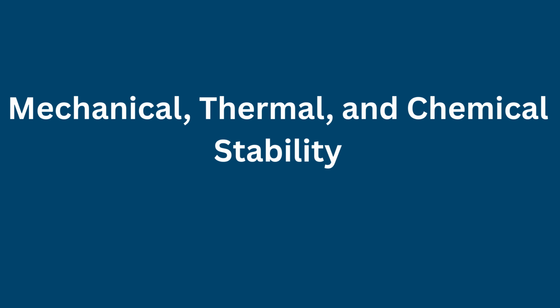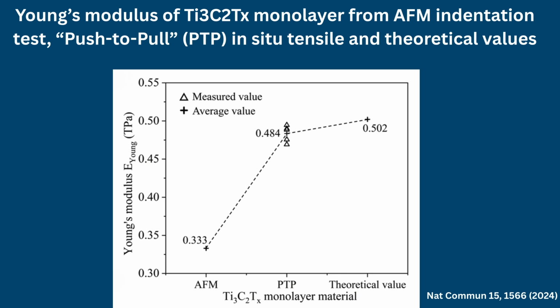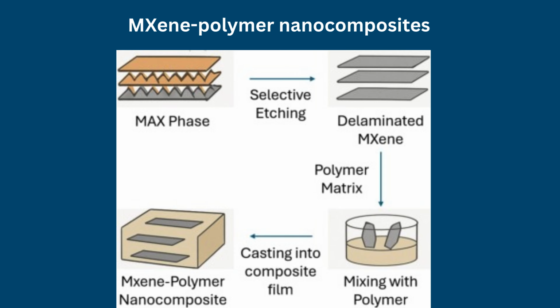Mechanical, thermal, and chemical stability. MXenes combine high stiffness with considerable mechanical flexibility. Single-layer Ti3C2Tx exhibits a Young's modulus of approximately 330 gigapascals, comparable to many advanced 2D materials. Their layered structure allows interlayer sliding, which contributes to flexibility and mechanical resilience under repeated deformation. MXenes also exhibit strong interfacial adhesion with polymers and ceramics, making them highly suitable for composite materials and flexible electronics.